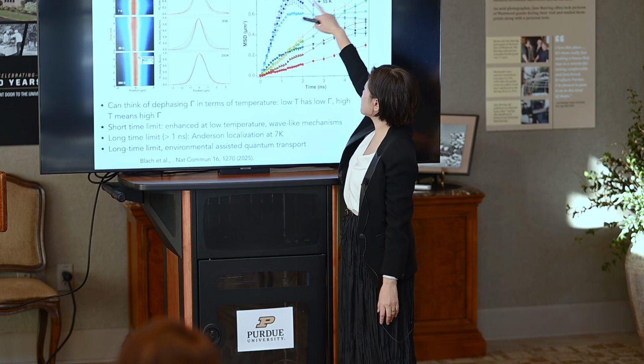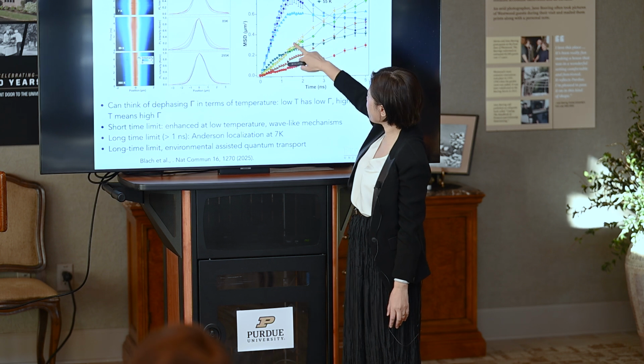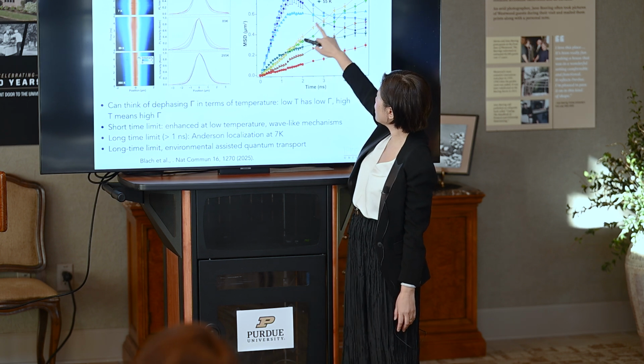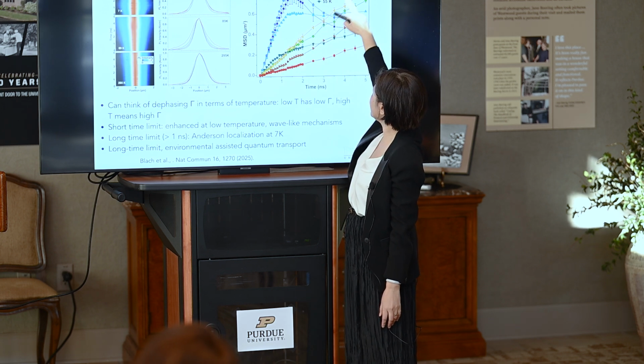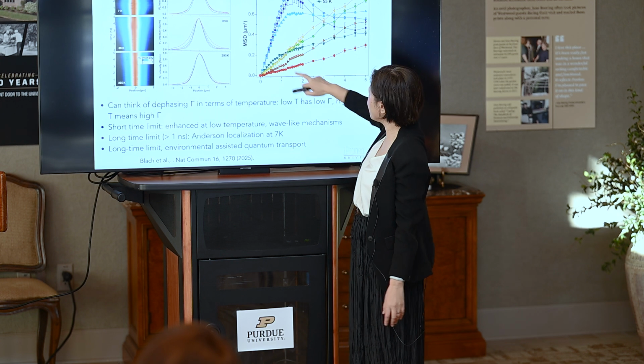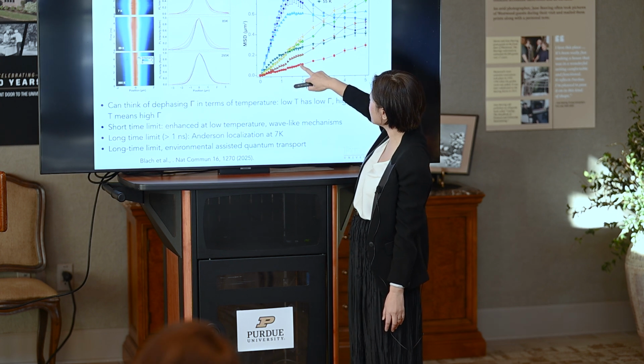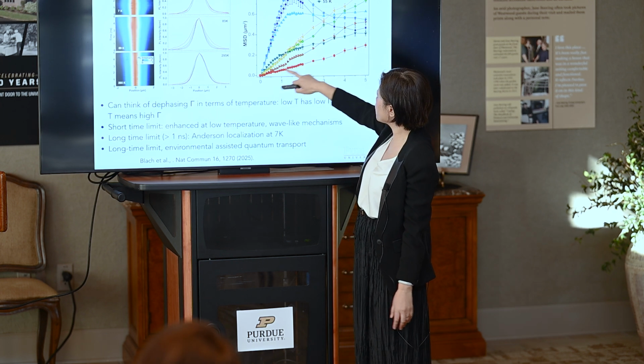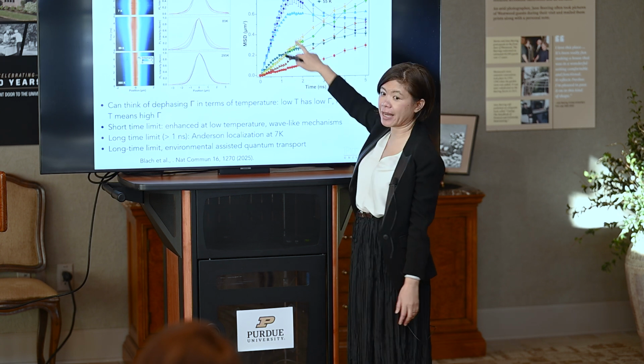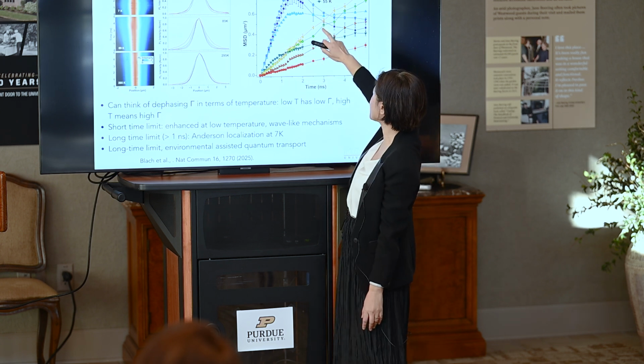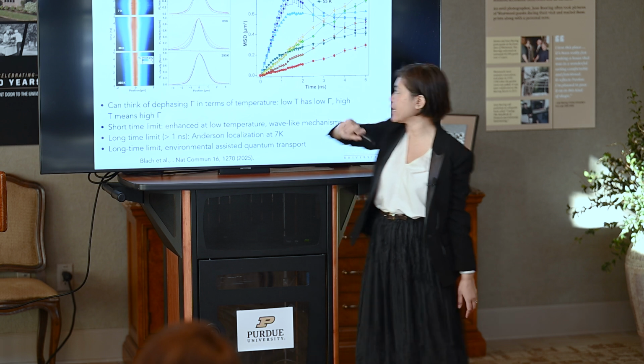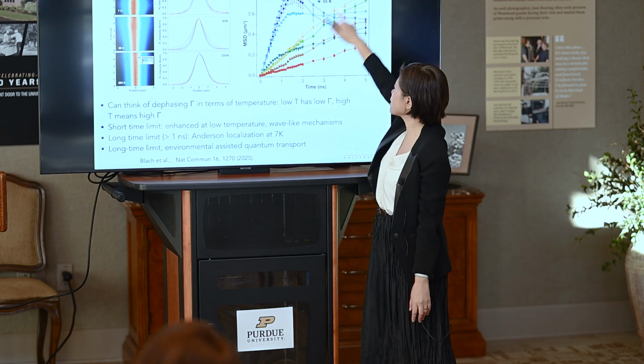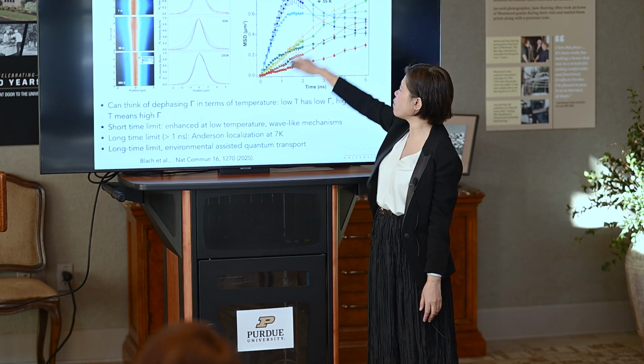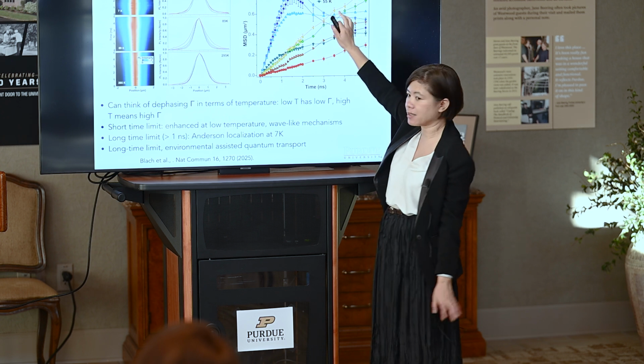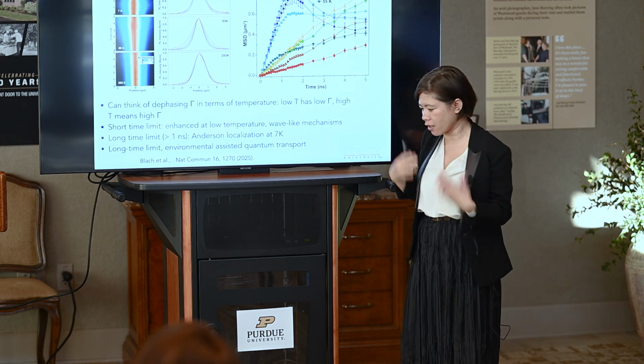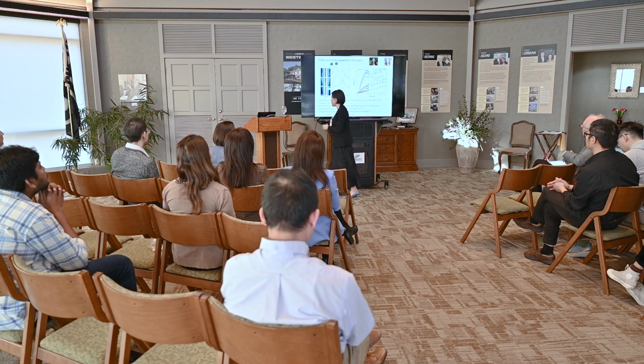But if I go up in temperature, initially the initial part slows down, but the later part actually keeps moving. And if I go to the highest temperature, at room temperature, it just becomes slower than this middle temperature. So a very intriguing thing that happened is that the total exciton propagation is the fastest at an intermediate temperature, not the lowest temperature, not the highest temperature.